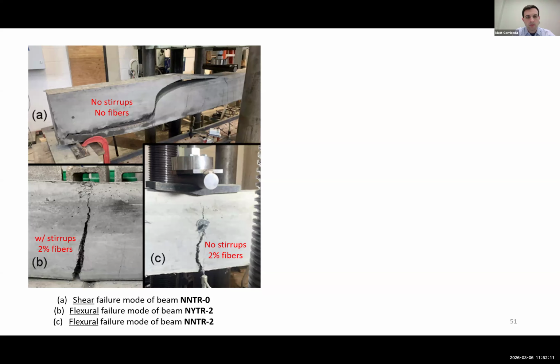So we tried a couple different variations of a rectangular section. The one in the top left did not have any shear reinforcement, nor did it have any of the fibers, and we got this really dramatic and clean looking shear failure, which was pretty crazy to watch in the lab. But when we did it we added the stirrups at the maximum spacing for ACI 318. We then added in the fibers, and we got this really clear isolated flexural crack failure.